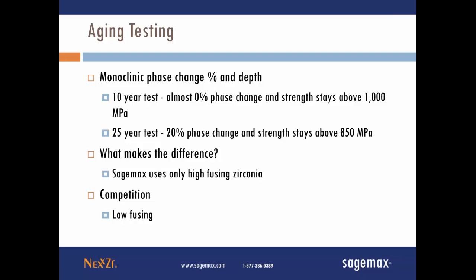Mm-hmm. Not so much with the low fusing. Low fusing is a very temperamental material. And most low fusing zirconia is unfortunately being over-sintered in order to achieve the higher translucency. So that would account for why their aging testing performance is so much worse, because they are not properly using the zirconia. That's true.